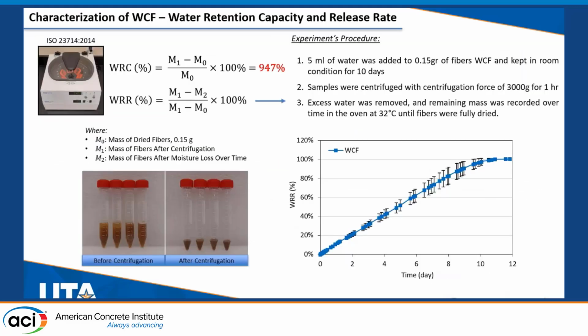Next, another property of interest is the amount of water that these fibers can absorb, because the magnitude of reductions in the autogenous shrinkage is a function of the moisture that is supplied by these fibers to activate internal curing mechanism and reduce the internal stresses caused by self-desiccation mechanism.